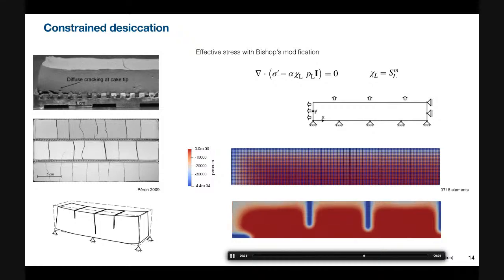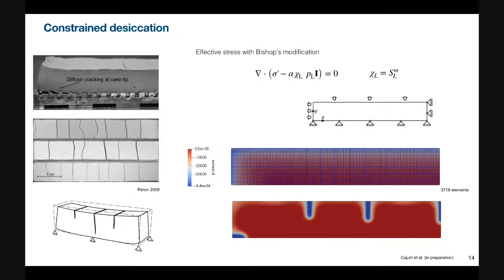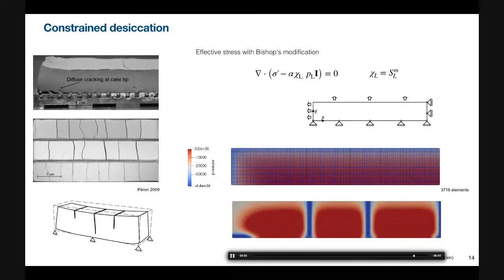And I'd like to highlight here that this is the computational mesh we used. As you can see, the mesh is very coarse. It's less than 4,000 elements, and the material is completely homogeneous. There's no heterogeneity in the material properties, and we didn't put any defects in the mesh or geometry that could initiate fractures. So these fractures are purely initiated by minimizing the system energy.